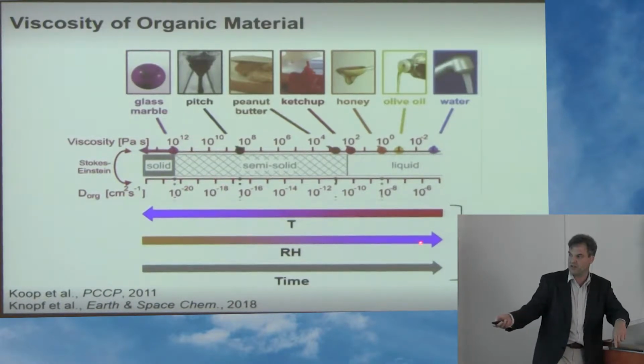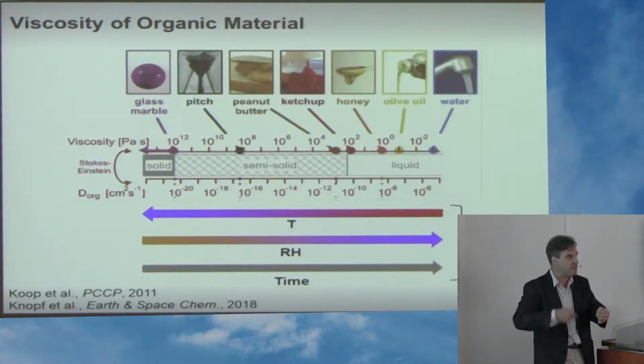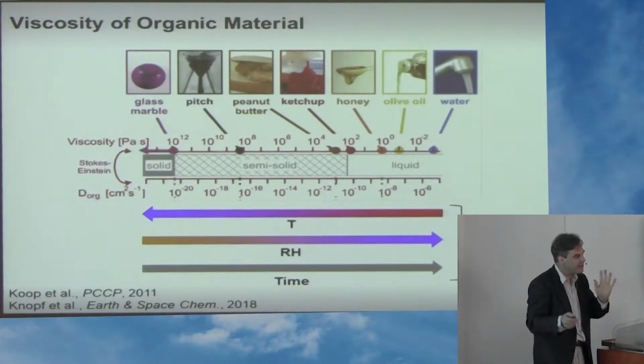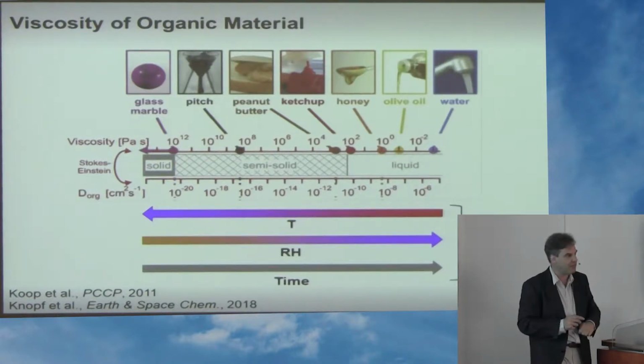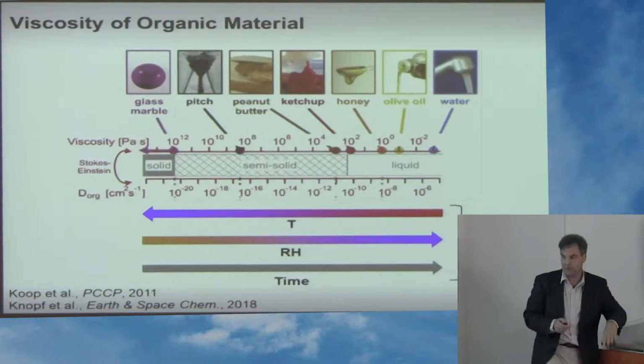If you increase relative humidity, you can maybe, depending on the hygroscopicity of this material, make them liquid again, but it all takes time. It's not instantaneous. Even if you expose them to high relative humidity, it may take half an hour till it is completely deliquesced, and that depends on the chemical composition of that material. That is where a lot of people do investigation.